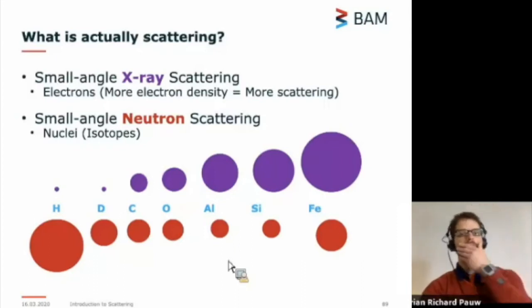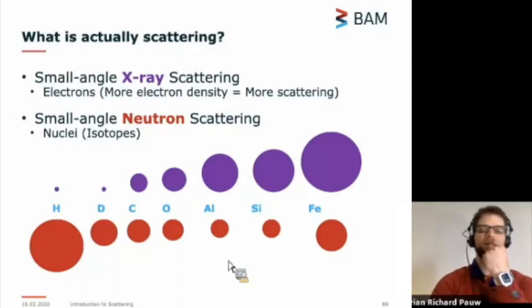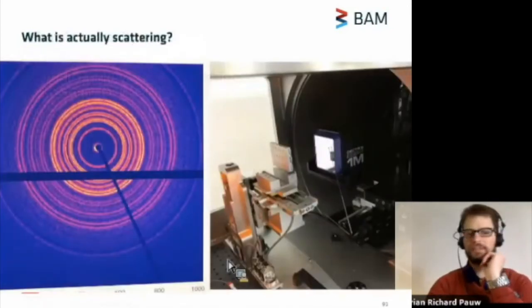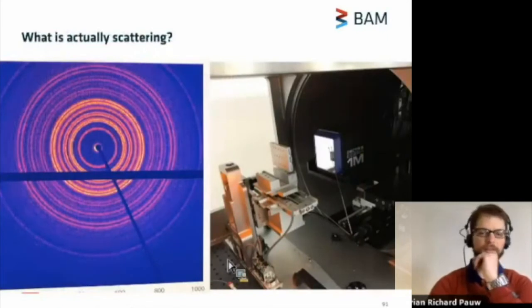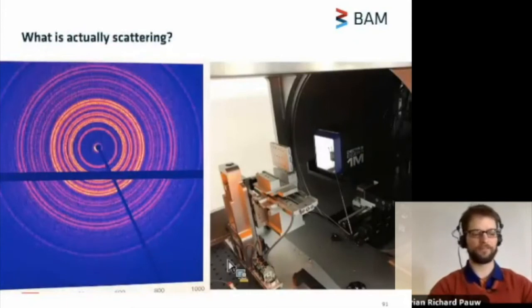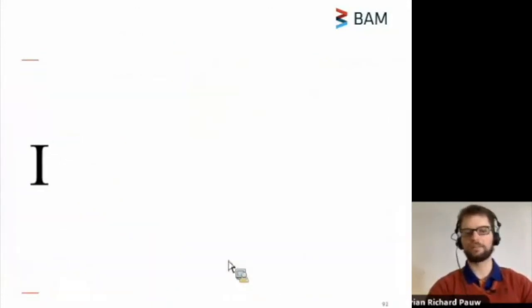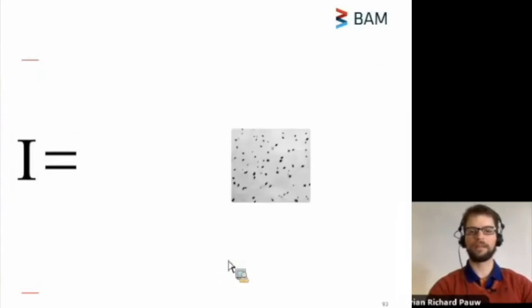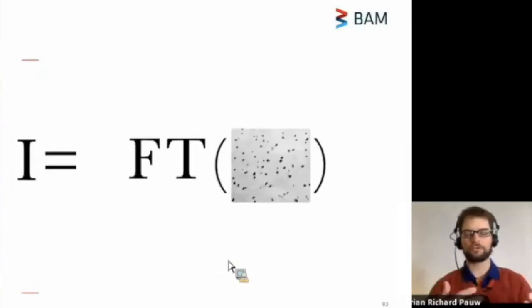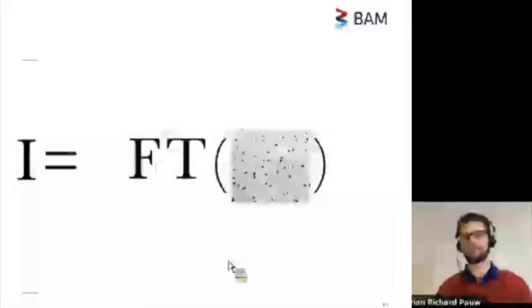So let's go back to scattering. What is actually scattering? Well, it turns out that the intensity that we detect on our detector is related to the electron density contrast in our sample. And the relationship with that is quite nice in that it is related by a Fourier transform. So in essence, our instrument is a Fourier transformer for anything we stick into the beam. And I find that really, really cool.